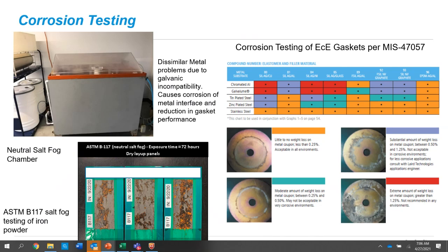On the right, you're going to see something a little bit different. With EMI, as I said, you've got a rubber gasket loaded with metal in between, most likely two metal or composite plates. So what you've got is a galvanic compatibility issue. Basically in a salt and water environment, that's a nice solution to conduct ions or electrons, and you're creating basically a battery cell. So depending on the properties of the filler in the elastomer and the properties of the metal it's going against, you can have metal ions acting as an anode and moving towards this and causing corrosion. What this table shows is two different things. It shows different metals, which would be the interface material, and then different types of conductive elastomers.